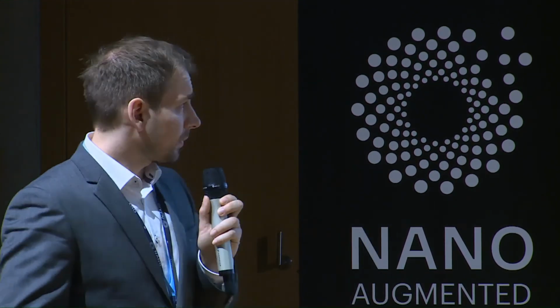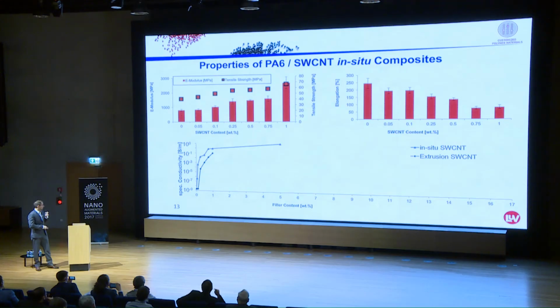All right, comparing to the extrusion compounds I showed you first, we have this curve in terms of conductivity. This is a logarithmic scale, so the difference is huge. There's a big benefit of this in-situ technique, you can see. The extrusion compounds perform about 1 to 2 decades below the in-situ compound.